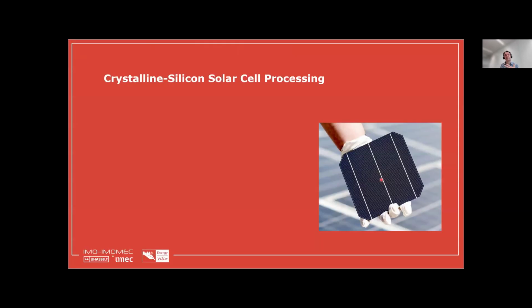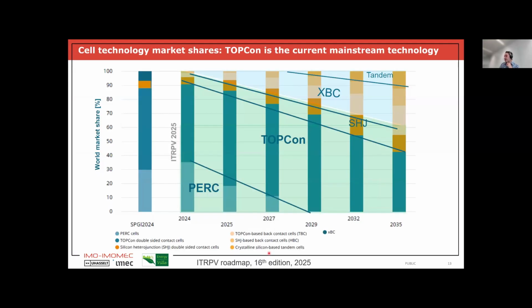So now we have talked a little bit about the wafers. How do the wafers now get processed into devices, into silicon solar cells, and what devices are being processed? So here I show you again a figure from the ITRPV roadmap of this year that appeared a couple of weeks ago. Here you see for 2024 the market share of different technologies. I don't have the time to go into the details of these technologies, but for the last 5 or 10 years, the so-called PERC, passivated emitter and rear contact structure, was basically the dominating technology that was being mass produced. But now, in 1 or 2 years' time, the domination of this technology has completely been removed. And now so-called passivated contact solar cells like TOPCon and silicon heterojunction are being produced in the biggest quantities. And I will explain these device types in the next slides.